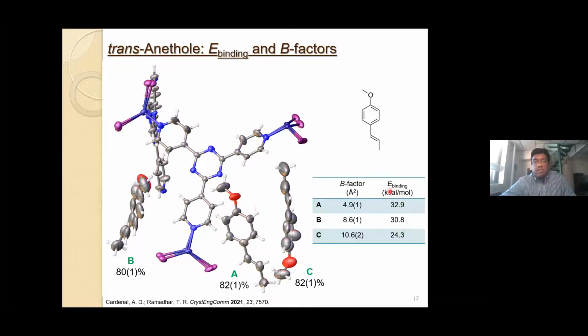It's the tightest binder. And what we also wanted to do was to look at something called the B factor, or a measure of disorder in the system. So molecules with low B factors have low disorder and small ellipsoids. Molecules with high B factors have high disorder and big ellipsoids. And we hypothesized that if you had a molecule that was bound tightly, we would probably have low disorder. And if you had a molecule that was bound weakly, then you have high disorder. And we did note that inverse relationship between the B factor, between the disorder, and the binding energy.